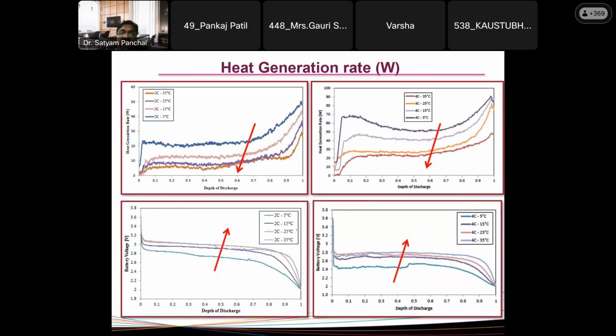After that, as I mentioned earlier, the heat generation method was used to calculate heat generation rate per second, meaning joule per second, that is in watt. This is the transient heat generation from a battery at different C rates. So 2C at 5 degree, 15 degree, 25, and 35 is provided over here. And in the same way, 4C at 5, 15, 25, and 35 degree centigrade is provided over here.